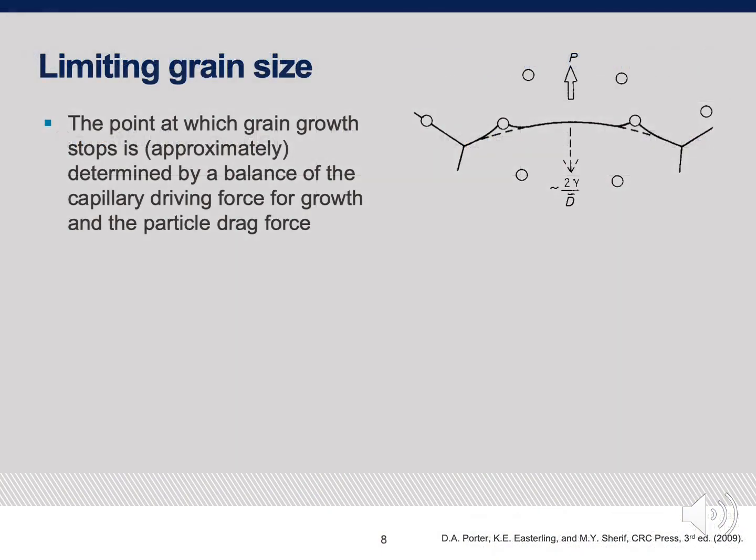And so eventually, this driving force that is afforded by capillarity will be equal in magnitude to the pinning force that is exerted by the particles or the pores in this material. So these particles exert a drag force, which is called P here, and naturally due to the curvature of the grain boundary, you have some capillary effect, some surface tension that is driving the growth behavior. Eventually, these 2 terms will be equal in magnitude.